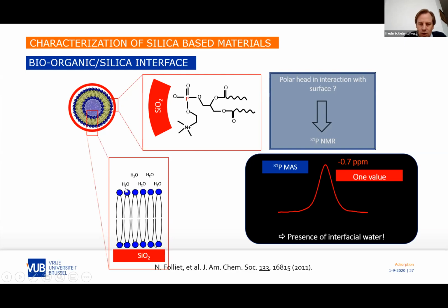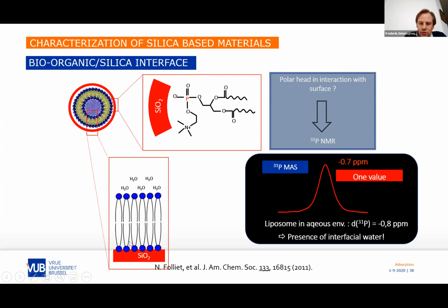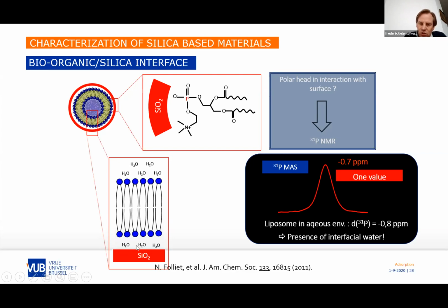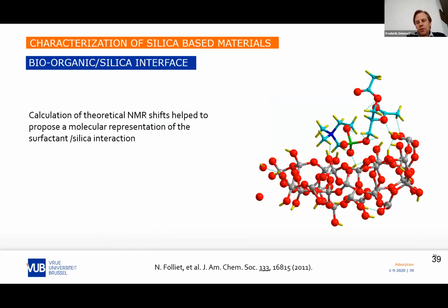What it means to us is that, in fact, this water layer is there, but you have a water layer between silica and water also present. And this is an example, but I can show you many of them, that this water layer is very typical and characteristic for silica. In many applications, if you don't calcine, you always have the presence of a water layer on top of it. I think I will stop with this here.